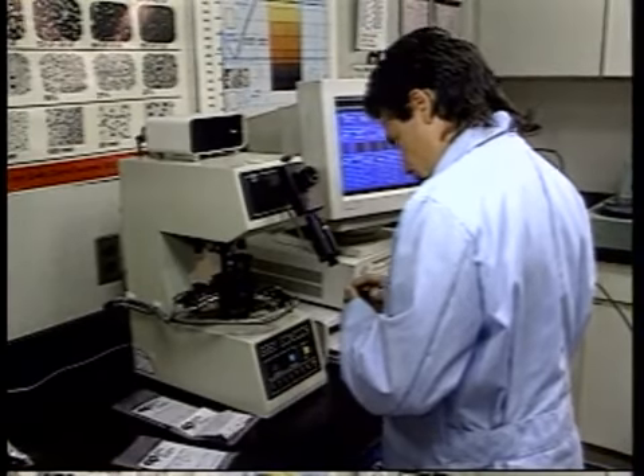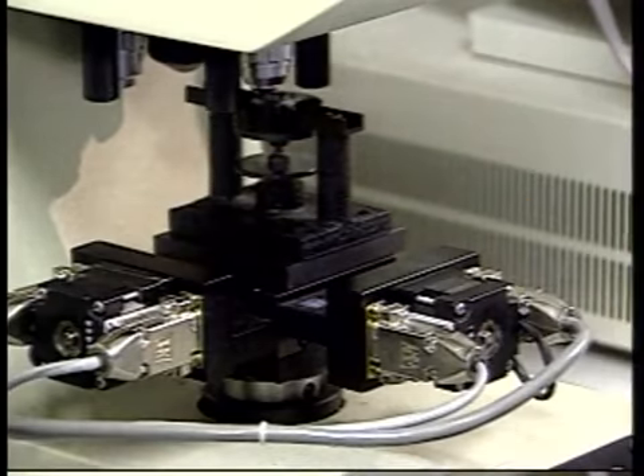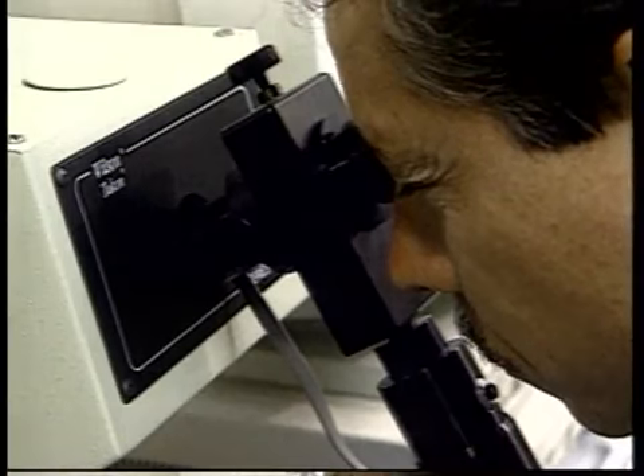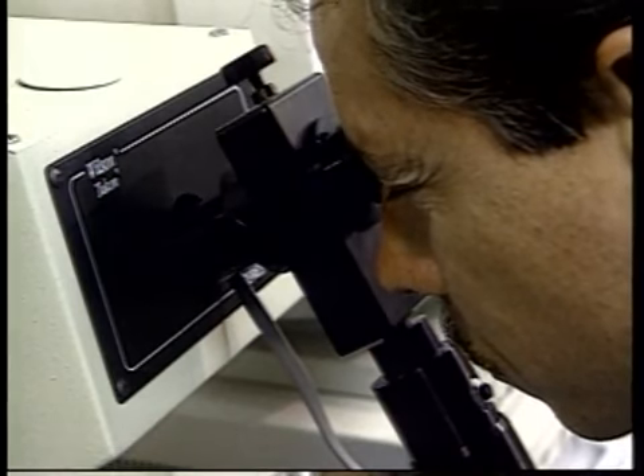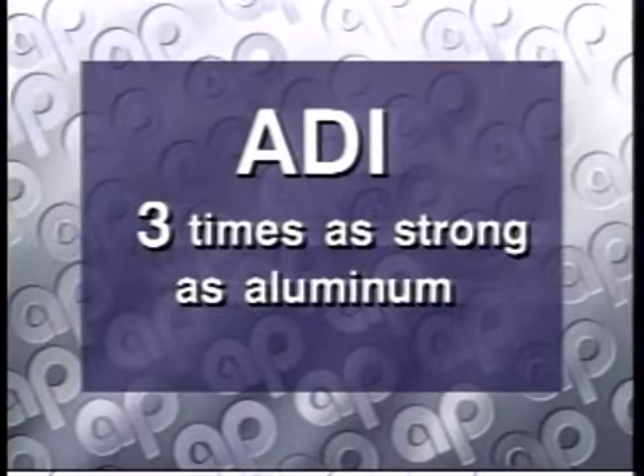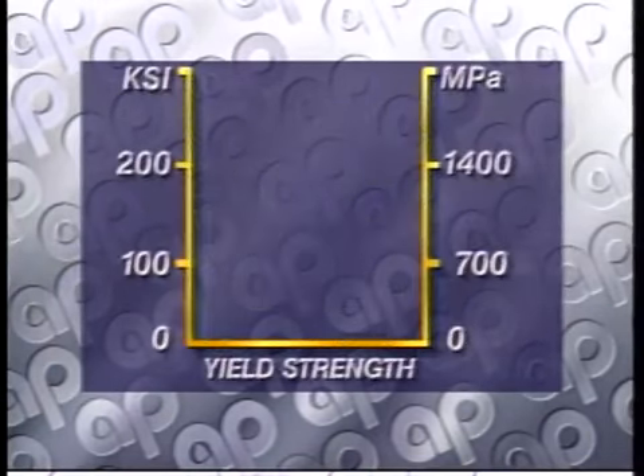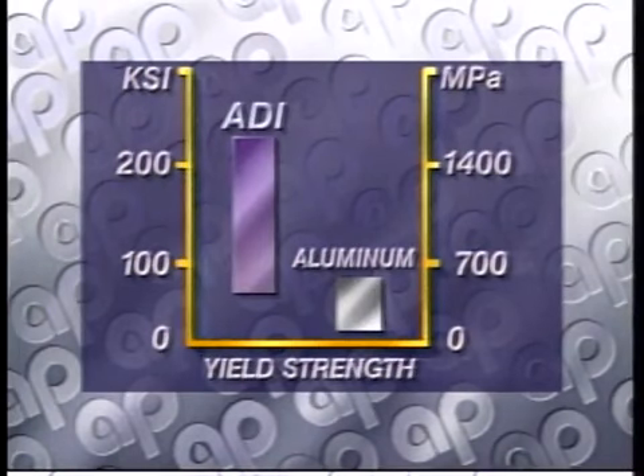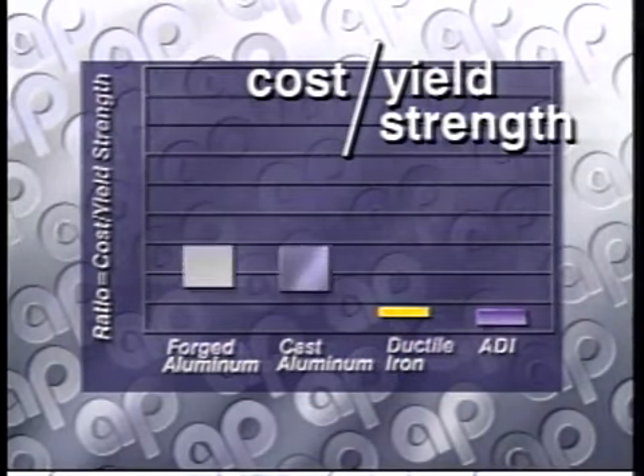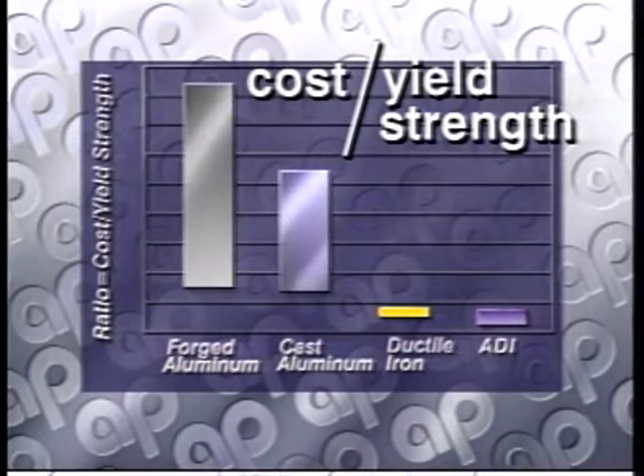Today, when one thinks of lightweight materials, aluminum comes readily to mind. But low density alone does not necessarily make the lightest component. ADI is typically more than 3 times as strong as the best aluminum castings and forgings, and ADI weighs only 2.5 times as much. Additionally, ADI has over twice the stiffness of aluminum. That means that a properly designed ADI part can replace an aluminum part as a weight savings. Given that aluminum can cost up to 10 times as much per unit weight, the cost benefits of ADI become apparent.